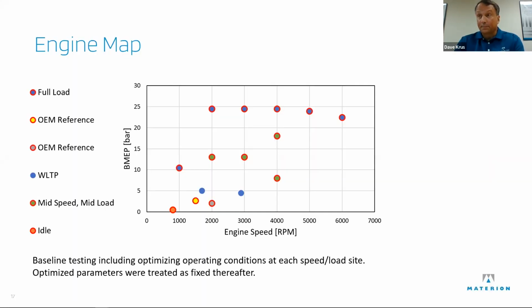This is the engine map in pressure versus speed. The purple with red circles is the full load curve that they ran. There were some OE reference points, things that they've done for other OEMs at Cosworth. The WLTP is a European emissions test, they test at those sites, and there are some other points that they put in. So what we did was have them baseline the engine as is, and then put in the Materion components and test it again to see what the changes are.